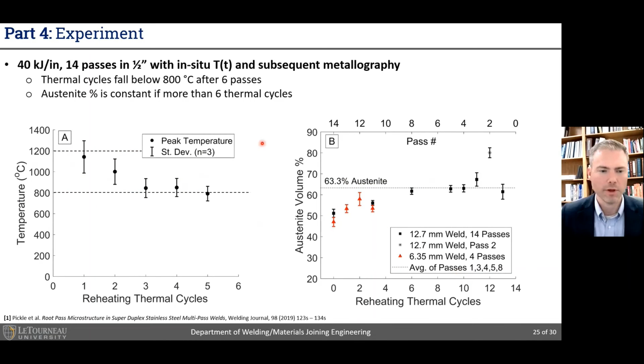So as a final experiment, we performed a 14-pass welding experiment using a 1/2 inch plate, where we took a similar kind of approach. We embedded a thermocouple for in situ root pass temperature monitoring, and then we did two things. The first was we plot the peak temperature as a function of these reheating thermal cycles. And significantly, what we find is that by the time one exceeds 5 reheating thermal cycles, one falls below this peak temperature of 800 C.